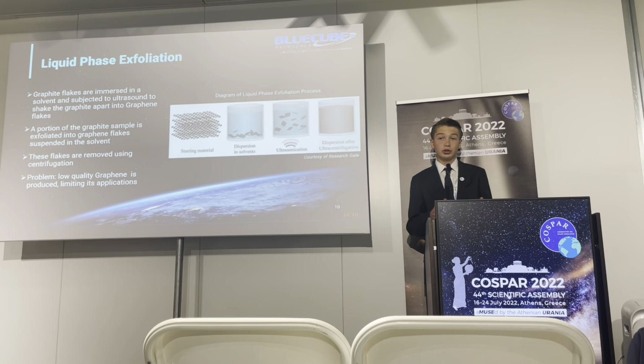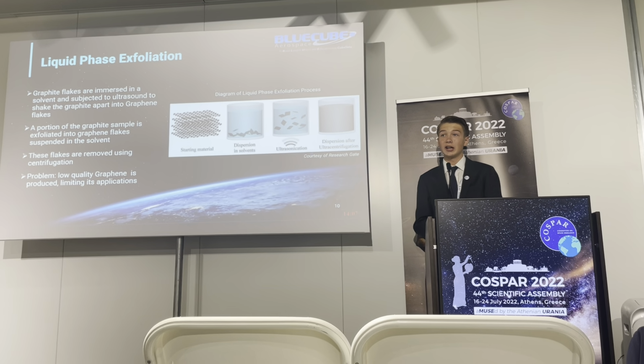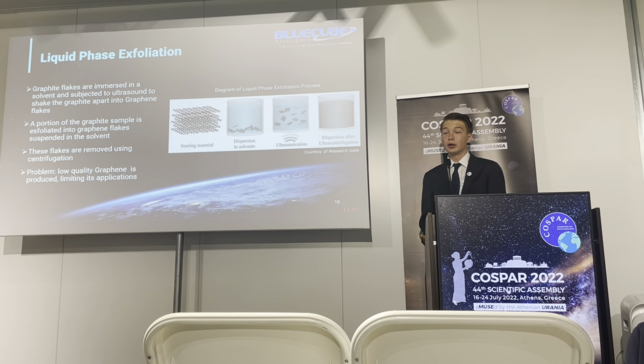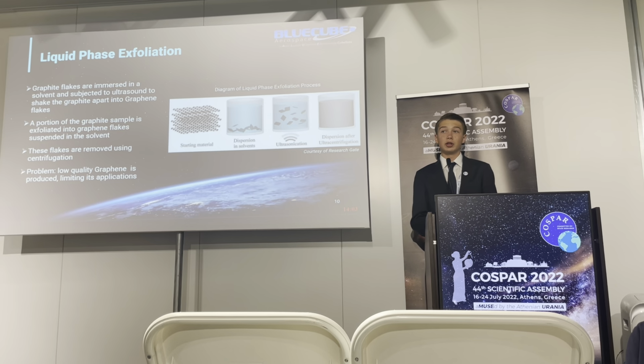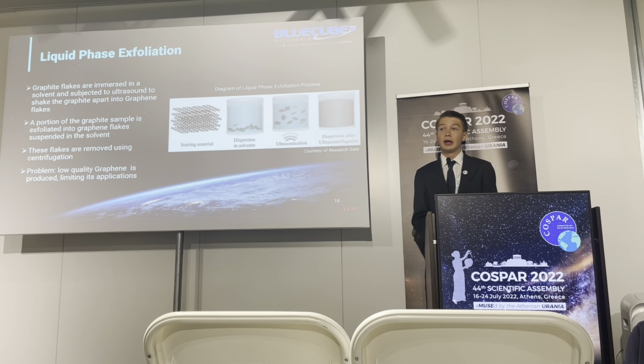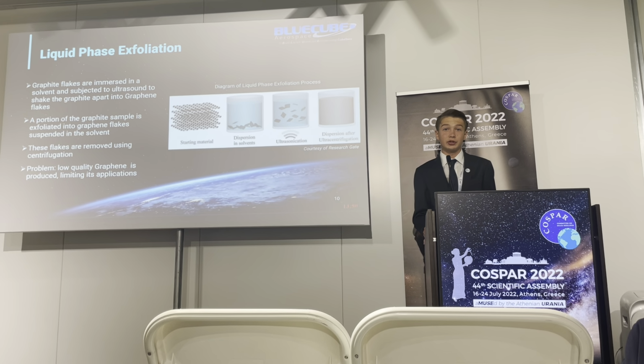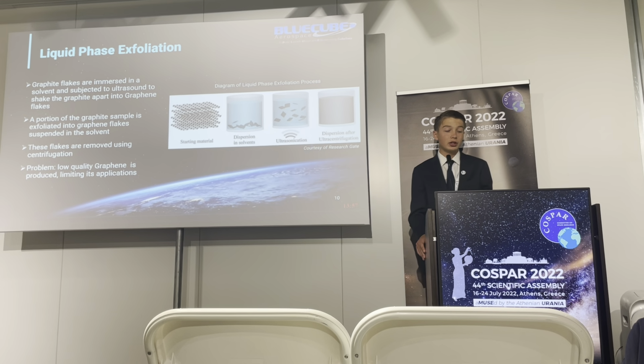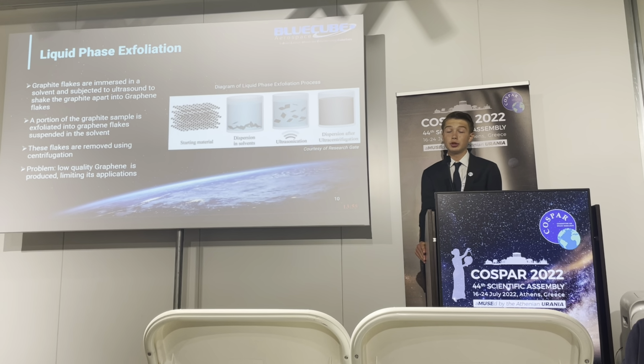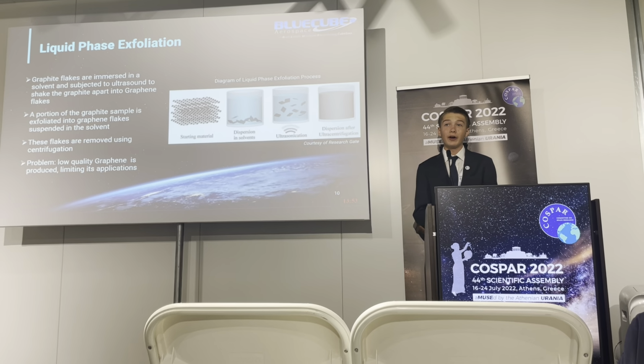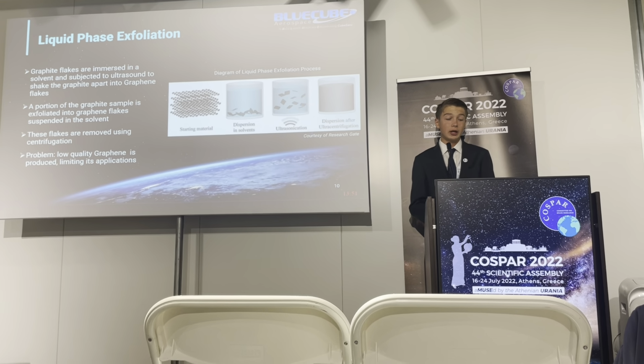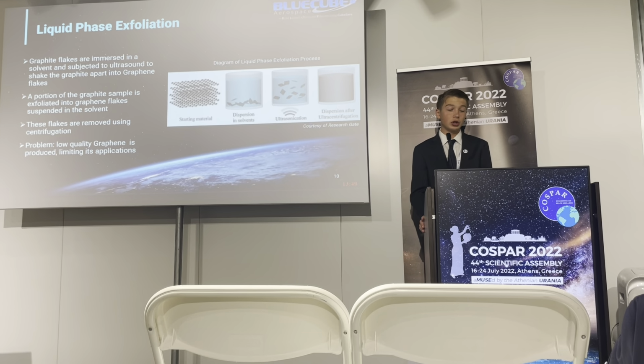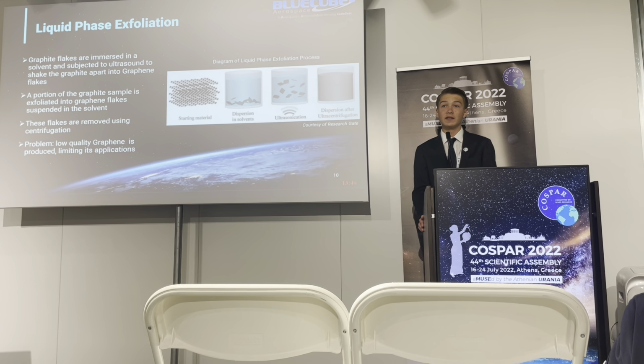Secondly, as an alternative to mechanical exfoliation and to produce larger quantities of graphene, the liquid phase exfoliation method was developed in 2008 and has been extensively researched ever since. In this method, graphite flakes are immersed into solvent and subject to ultrasound to shake the graphite apart into graphene flakes. And a portion of the graphite sample is also exfoliated into graphene flakes that are suspended in the solvent.